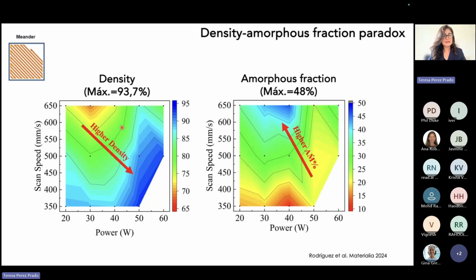And if you look at the density map, this is the same density map I showed you before, the density changes in exactly the opposite way. So it increases when we increase the laser power and we decrease the scan speed. So here we have two magnitudes that we want to optimize simultaneously, and within our processability window, they just change in exactly opposite directions, no? So this is what we call the density-amorphous fraction paradox, and this is something that we definitely need to overcome if we want to solve this challenge.